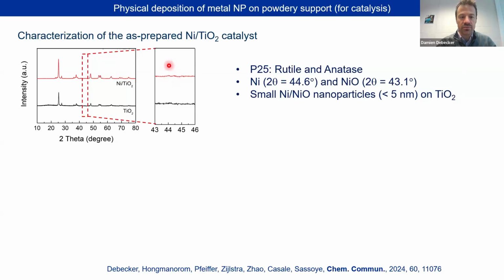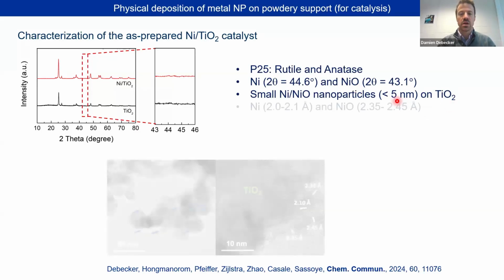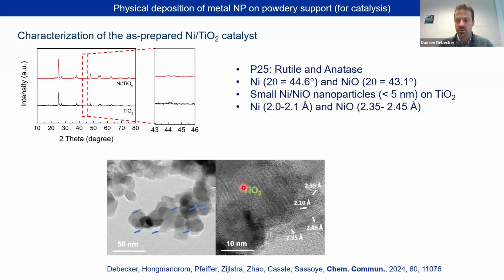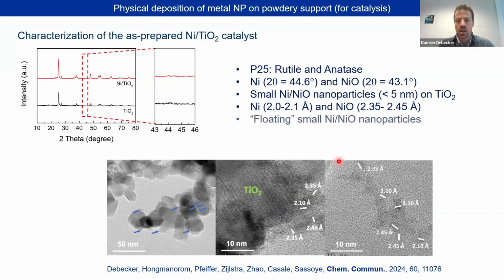But if you're very careful, you can see the signature of nickel and also nickel oxide, because you have surface passivation if you manipulate them in air. They are quite small, apparently smaller than 5 nanometers. And indeed, if you look at them in electron microscopy, this is what you see, and you recognize the facets or the d-spacing for the two phases here.